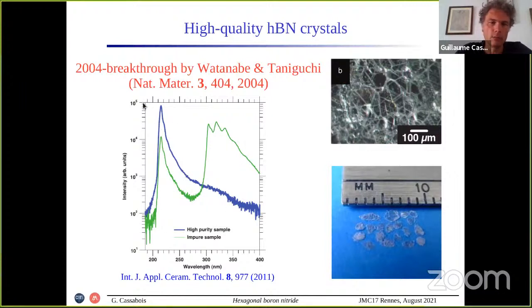The breakthrough of Watanabe and Taniguchi was to synthesize these small single crystals of high quality and high purity. This was demonstrated by cathodoluminescence, as shown here in the panel, where you have the cathodoluminescence spectrum in blue of the high purity crystals of Taniguchi, and in green of the typical samples that were available before the work of Taniguchi. There is this huge emission around 300 nanometers. This is very important. Pay attention to the wavelength scale here. We are dealing with the ultraviolet, deep ultraviolet, between 200 and 400 nanometers.